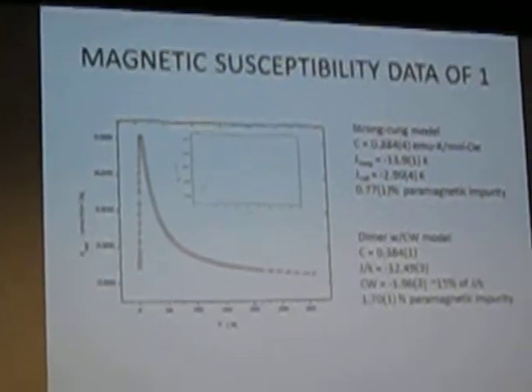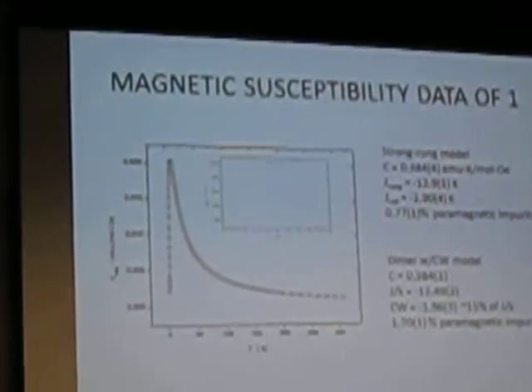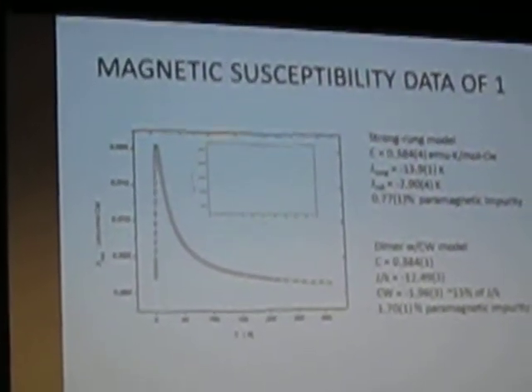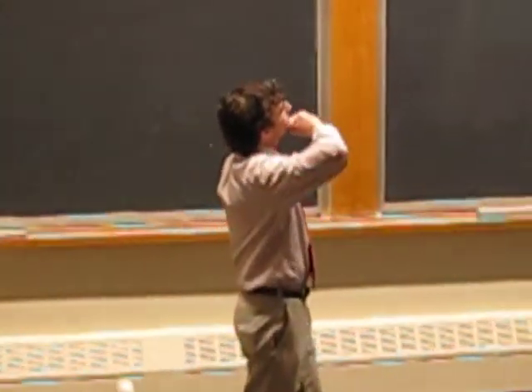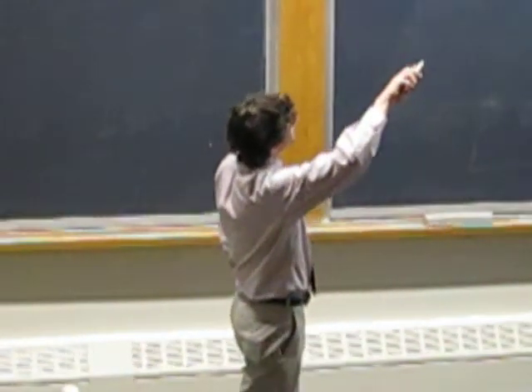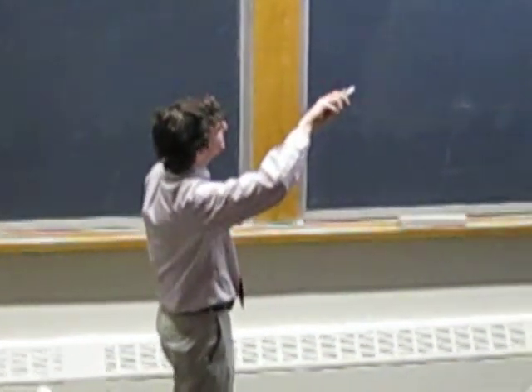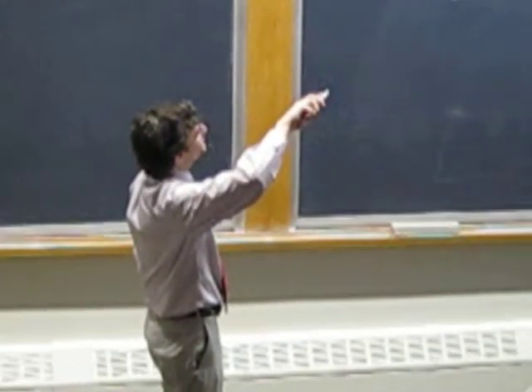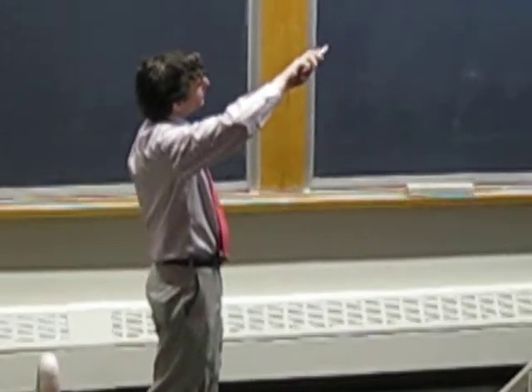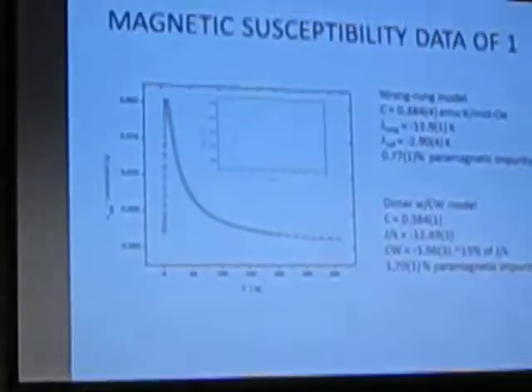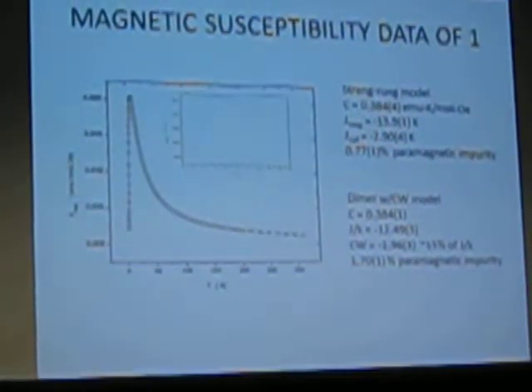So this could mean that it could be either a dimer, or an alternating chain, or a ladder. But based on the crystallographic data, it makes more sense to be a ladder. But I fit it to both parameters using a dimer with the Curie-Weiss model, but we have to be careful because a Curie-Weiss model with the Curie-Weiss correction of greater than 5% is an invalid model, so we have to make sure that we don't use invalid models when we're describing the data.